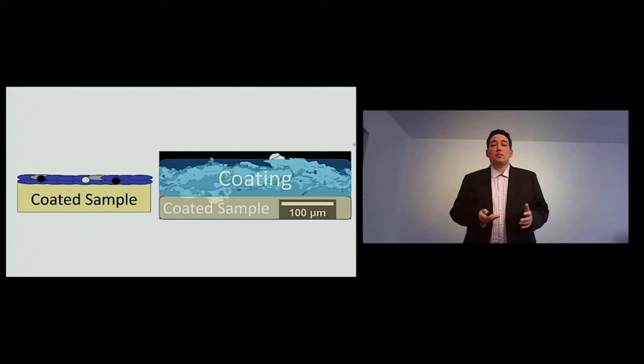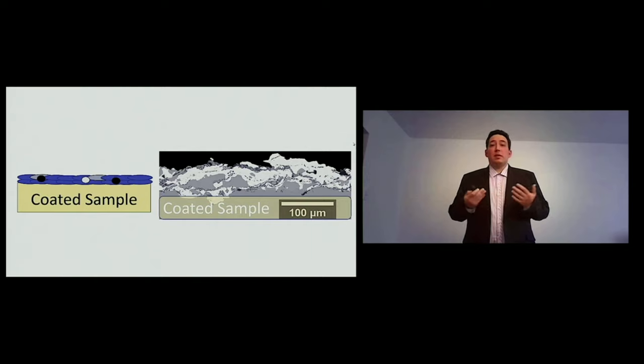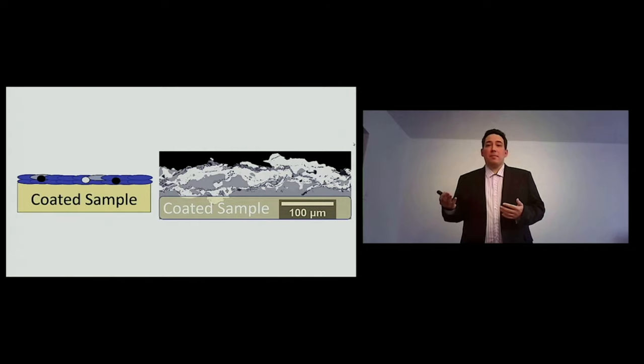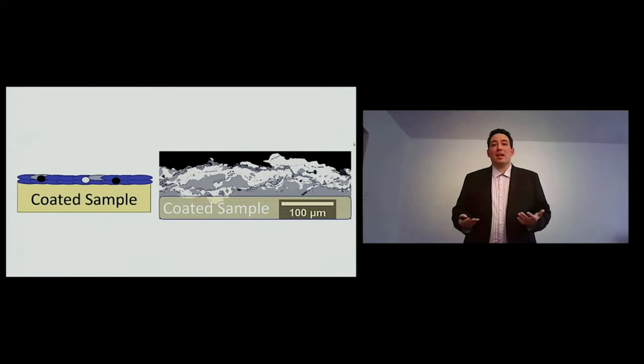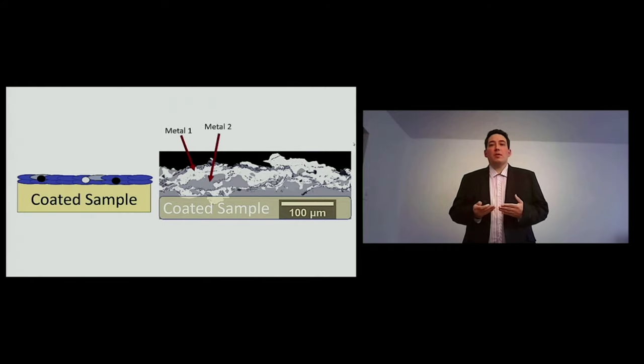Well, let's remove this box for a moment so we can see the coating. In this type of image, it's an electron microscopy image, different contrasts have different meanings. What I mean is that different materials have different atomic weight, and then it shows different in the image. A white contrast means a heavier element, and a darker contrast means a lighter element. Based on that, we can see that we have the metal one, which is the bright one, the metal two, which is the gray one, and we have those small particles that are the ceramic one.